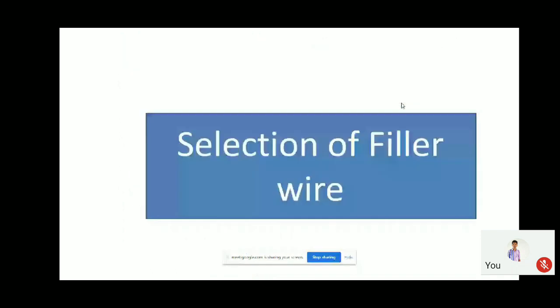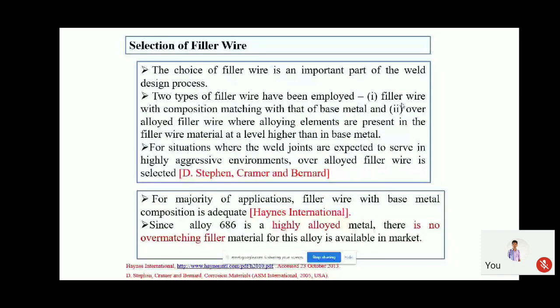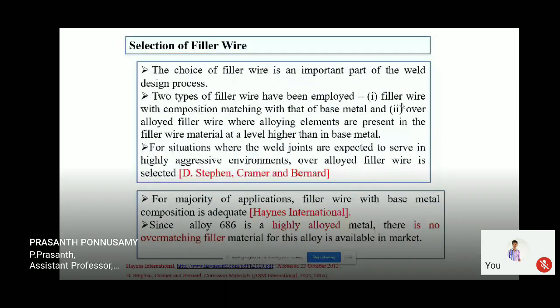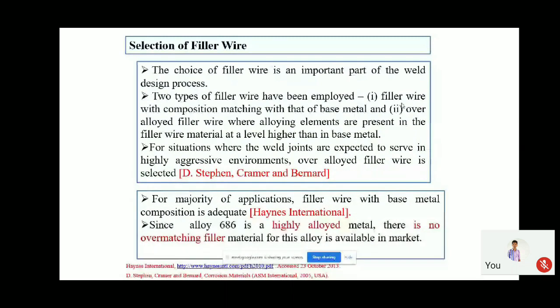Next one is the selection of filler material. Selection of filler material is one of the most important things in weldment design, because if you are not choosing the proper filler material, obviously the weldment will fail. So usually there are two different types of filler material that can be selected. One is the filler material composition which is equal to the base metal composition. For example, we know very well stainless steel 304 or 316. When we are going to weld 304 or 316, we will always go for 304 or 316 filler material. But if you are putting your material in a very high temperature or corrosive environment, we can go for the higher alloyed material, meaning the composition should be higher than the base metal composition. In that case, we can use the over-alloyed filler material.